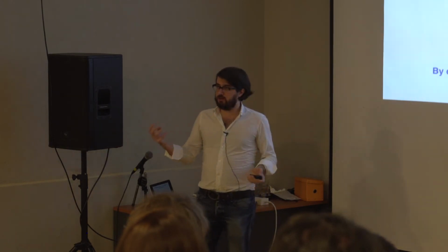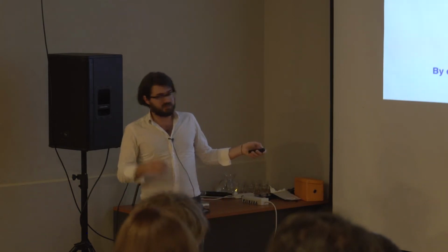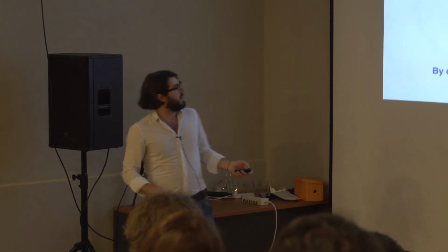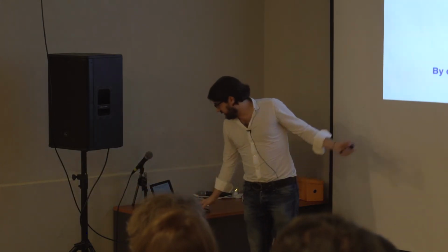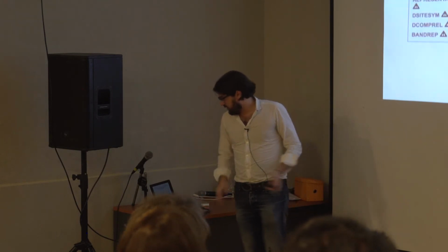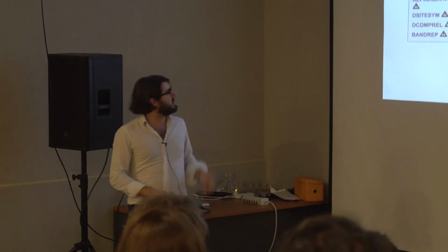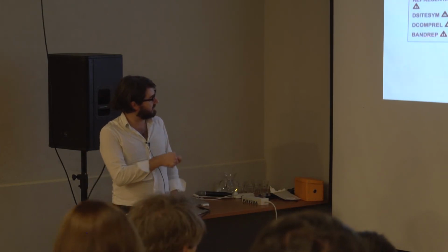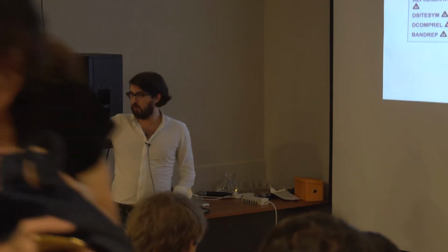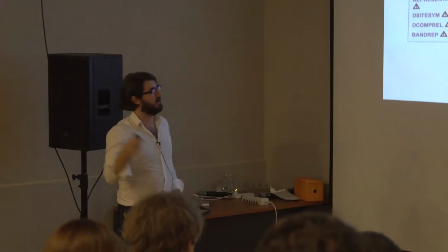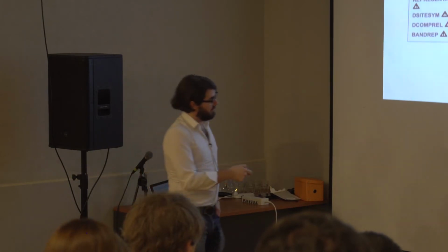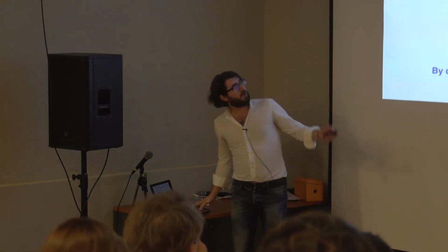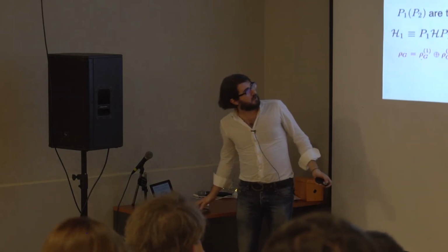Now, by construction, the way we're constructing it, every one of these band representations has an atomic limit because we constructed it from atomic orbitals, and all atomic limits yield a band representation. Okay, so for example, these are all now tabulated on the Bilbao crystallographic server. You can just click on the band representation, put in what orbitals you want, on which lattice you want them, of whatever group you want them, and obtain all these eigenvalues here.